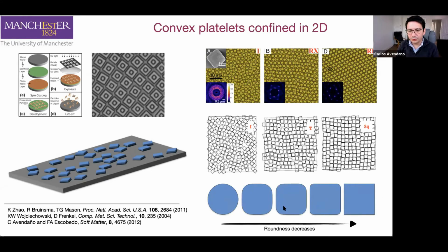So the model to do this, Charles and Federico will be quite familiar with this. We decided to use the model of a spherocylinder. The overlap algorithm for a spherocylinder is relatively straightforward. This model is completely characterized by the length of the cylinder, something that you tend to call the aspect ratio. So that's the length of the cylinder divided by the diameter of the cylinder. When the aspect ratio is equal to 0, so when the length of the cylinder is equal to 0, then you have a perfect sphere or perfect circle or perfect disk. Or when the aspect ratio is very large, basically you have almost like a line.